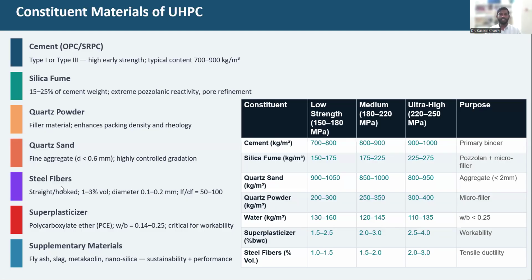And in UHPC, steel fibers are one of the most important combinations of materials. Particularly, we use different types of steel fibers, such as straight steel fiber, hooked end steel fiber, and other types of steel fibers are also used, which I'll explain in a while. Typically, the steel fiber will have a volumetric percentage of 1 to 3%. That's a typical percentage that we can use. Again, this 3% is the higher bar. So we can limit that to 1.5 or even 2% also, which will yield better strength as well.